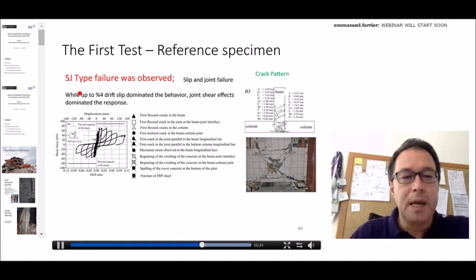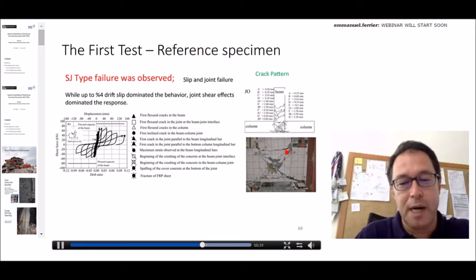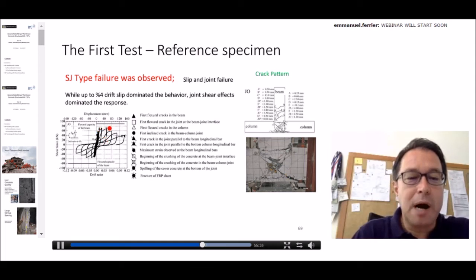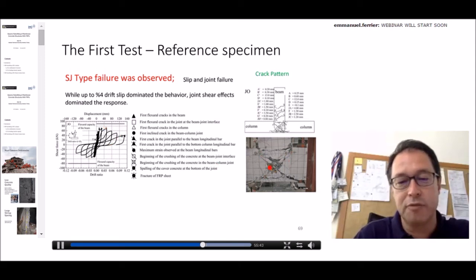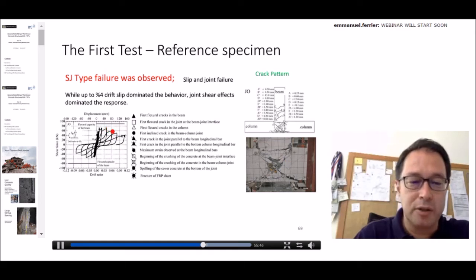Interestingly, the first specimen, which is the reference specimen, failed basically because of slip of the beam longitudinal bars first. I'm going to explain this mechanism in the next slide, which somehow gave us a kind of pseudo-ductile behavior until 4% lateral drift. Then we had significant damage on the joint, and the joint shear damage caused a more rapid strength decay in the post-peak area.